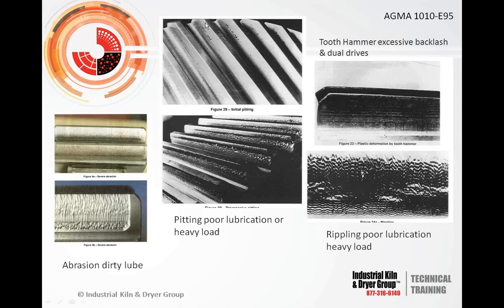When you're first starting out with pitting, you'll see real small lines like this. If you can catch it at this point, and you see it on one side of the pinion and gear and not on the other, it's a good indication that you've got a little bit of misalignment. It would be beneficial to do an alignment check on that gear and pinion to get it lined up so that you have full contact. The other thing you want to do, if you see this type of wear occurring on the gear and pinion, is put that infrared gun on there and see what the temperature difference is.